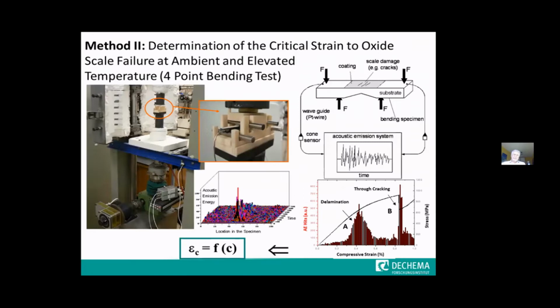Now, later on, we developed another technique for measuring the critical strains, and this is the 4-point bending test. The 4-point bending test is more accurate. You have a better, more accurate situation concerning the stress situation in these oxide scales on the surface of such a 4-point bending specimen. And you can also locate the events on the surface of the specimen. If you have two sensors, you can find out where is the signal coming from. Is it coming from here, or from here?